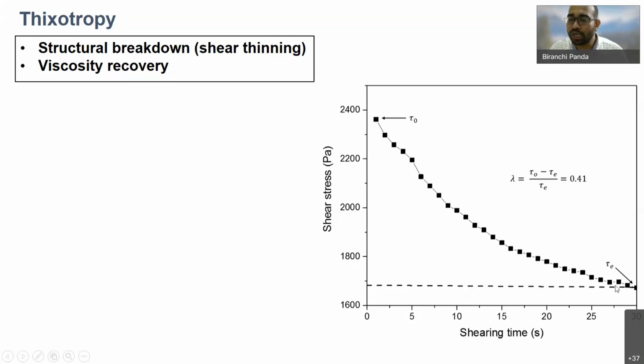If this equivalent value is not low, it means that even after applying a high shear rate, the material is not completely broken down, and the shear thinning behavior is not promising for your material. So this is how we characterize the shear thinning behavior, which tells us the effect of pressure on the material during pumping. If this breakdown is greater, we can easily pump the material without any problem. So it is all about characterizing the pumping process through the shear thinning protocol.